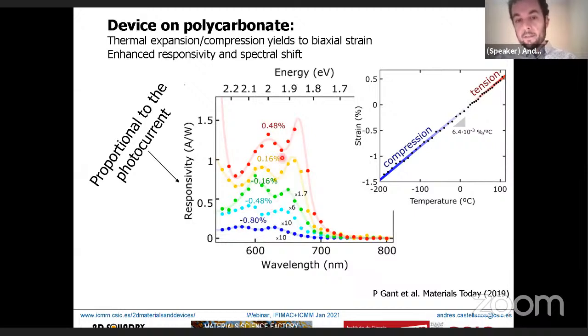We can achieve these strain values by changing the temperature of the substrate. We can go all the way from minus 200 degrees, liquid nitrogen, where we have minus 1.5% compression, all the way to 110 degrees, our maximum, which gives plus 0.5% tension. We are limited by the melting of the polycarbonate, actually.